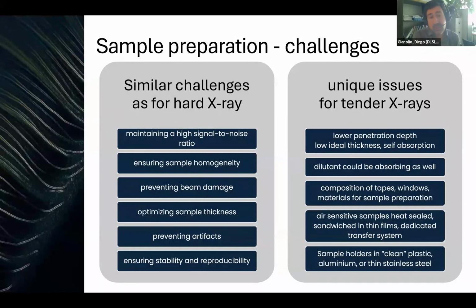Other issues are more unique due to the fact that we have a lower energy. A consequence is, for example, that the penetration depth of the X-rays into the sample is lower. And this causes multiple issues. One is that the ideal thickness of the sample is much smaller, and then it makes it difficult to prepare very thin samples that can still be mounted on the beamlines. And of course, there is also the problem of self-absorption. When you cannot make thin samples, it would affect the quality of the data. I will talk more in detail about self-absorption later on, so I won't spend too much time now.